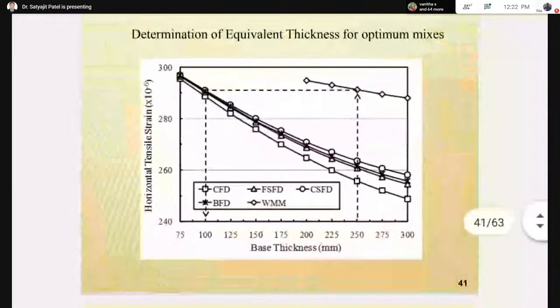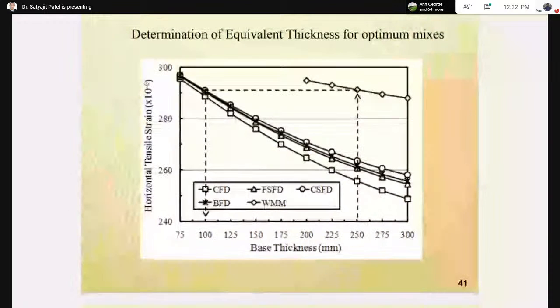Similarly, the equivalent thickness. Based on that horizontal tensile strain, which is shown here in the previous table, if you plot it with the base thickness, the top line indicates the WMM, wet mix macadam. The bottom four lines correspond to the cemented waste material. So you can find out the equivalent thickness. That is, 250 mm of WMM is equivalent to how much? Around 100 mm of waste material. So see the thickness difference.